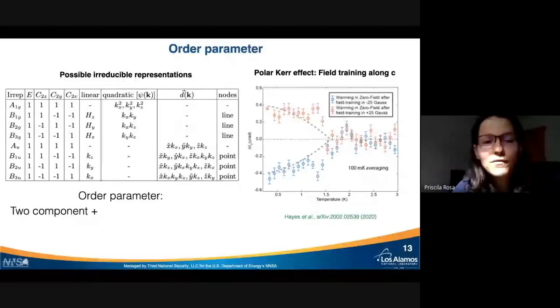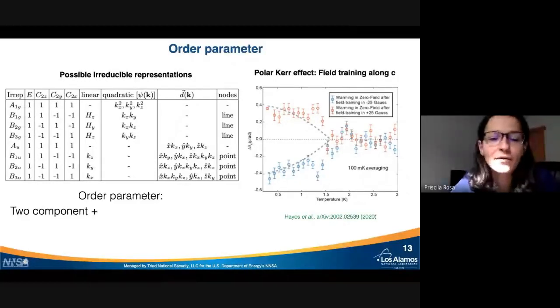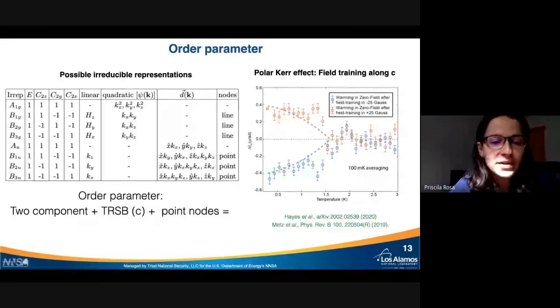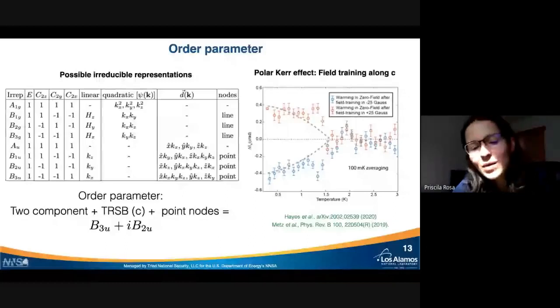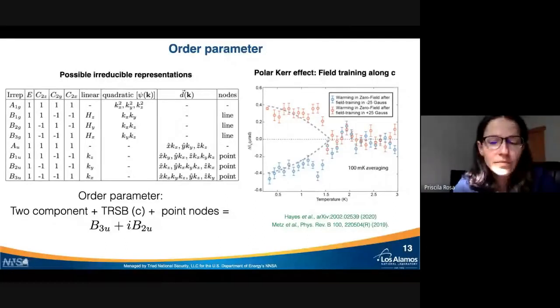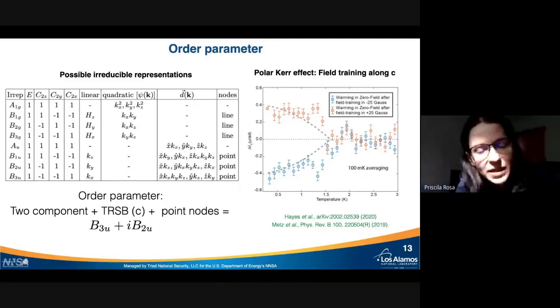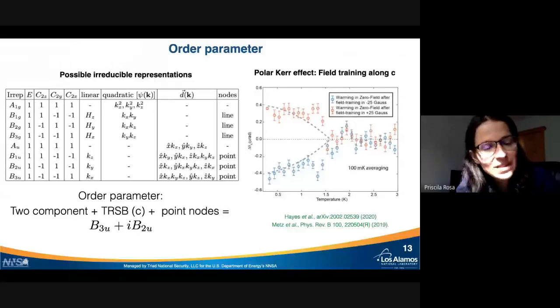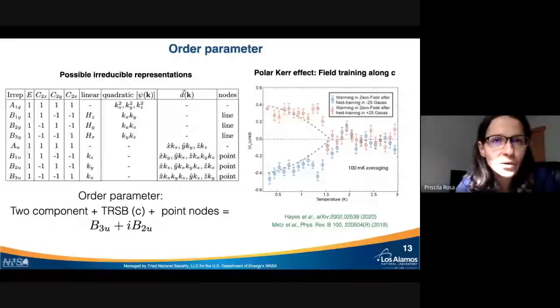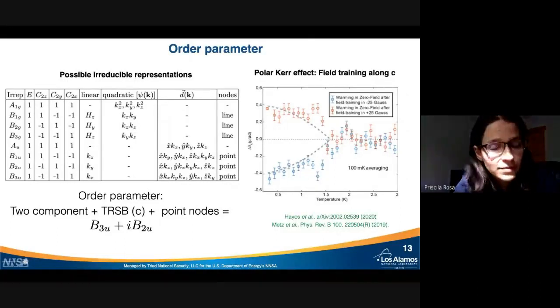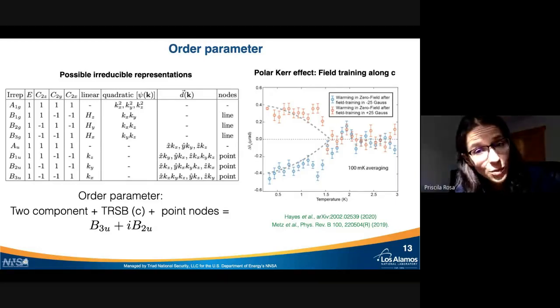And the only way to have a B1G coupling is to have an order parameter that is a B3U plus iB2U. And I know this is a little bit technical, but I just want to get to the point that if we take this result into account, the only way really to have the superconducting order parameter written down in a consistent way is this. But I just showed you in the previous slides, both the results from our group point towards an antiferromagnetic component being relevant, and second, other theoretical approaches showing that other combinations of these irreducible representations could also be possible.